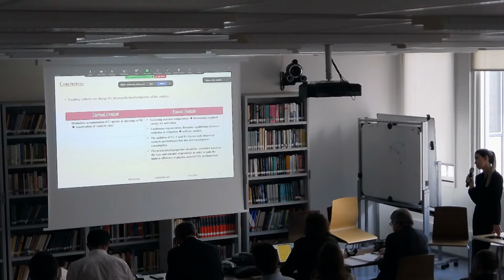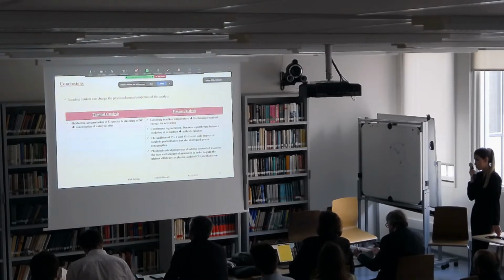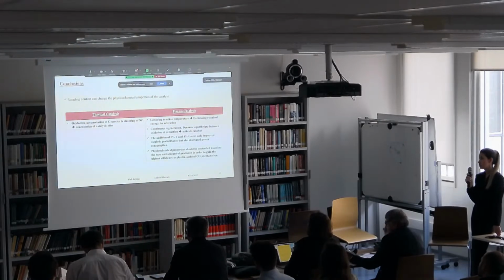So to conclude these two parts of the study, under plasma condition there is a lower temperature, so a lower activation energy is needed, while under thermal there is a higher temperature and a higher need of energy. We also saw that there is a reoxidation process under plasma catalysis which keeps the catalyst active, while the high temperature under thermal condition brings the possibility of catalyst deactivation and carbon deposition. Also, different types of promoters such as yttrium and lanthanum with different amounts of loading improve the catalytic performance. But in general, the physicochemical properties should be controlled based on the type and amount of promoter in order to have the highest efficiency in plasma CO2 methanation.